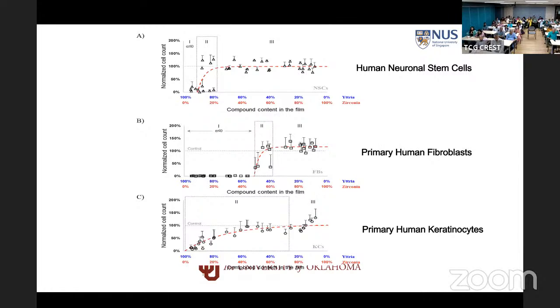I'll give you an example. This is a binary phase diagram, with yttria on the left side and zirconia on the right side: yttrium oxide on the left, zirconium oxide on the right. I'm varying the composition of my substrate from left to right. You see, neuronal stem cells hate yttrium oxide. They don't want to grow on it. But the moment I get to about 10% zirconia, it jumps up and starts growing very nicely. Human fibroblasts require roughly 50% before they start growing. And keratinocytes grow very gradually. But in all three cases, yttrium oxide is not a preferred substrate. You can see that.